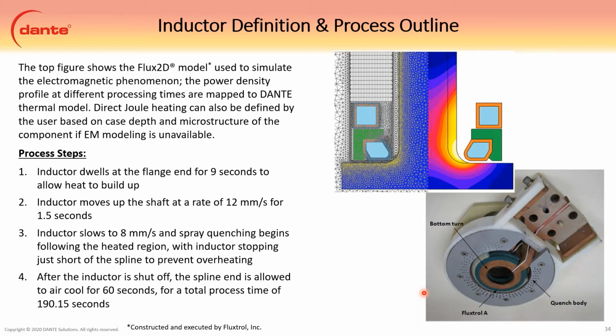So we can play with power levels. What happens if we put more power to it, or less? You can also manipulate the frequency by modifying how deep the Joule heating goes, because frequency essentially dictates how deep the electromagnetic waves get into the part. This process consisted of a 9-second dwell at the flange to let the thermal energy build up. The inductor then moved up the shaft and slowed as the spray quenching began. Then the inductor was shut off once it got near the top to keep the end from cracking.